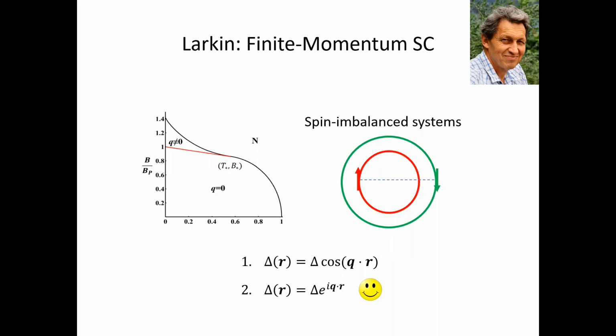If you have a metal with a spin imbalance so that the Fermi surfaces of spin up and spin down electrons are of different size. And in this case, pairing between spin up and spin down electrons is most natural on the Fermi surface of the two. And there, because of the Fermi surface mismatch, you end up with Cooper pairs at finite momentum.